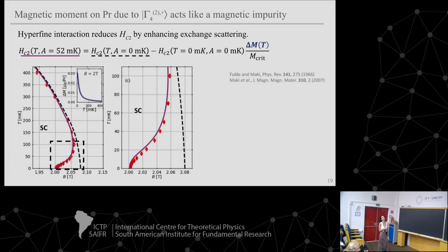So we tried this model from Fulde and Maki, which is quite old by now, but basically it just looks at the effect of adding delta M, which is magnetic impurity, into the superconducting state. The black dashed line is taken based on the high temperature data where there are no hyperfine interactions. And then the purple one is when we include the hyperfine interaction, giving a delta M that we calculate from the hyperfine mixing of the levels. This is what the delta M looks like based on our mean field calculation. You can see that the purple line fits extremely well, so this is a really good description of what we see in the suppression of the superconductivity.